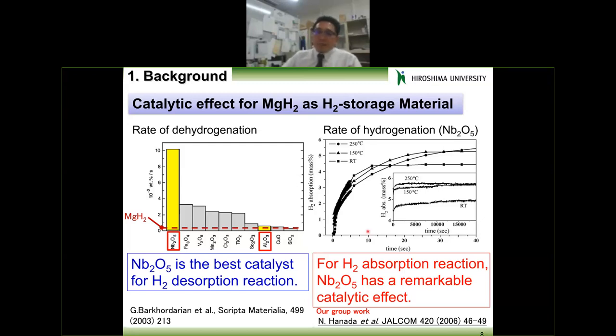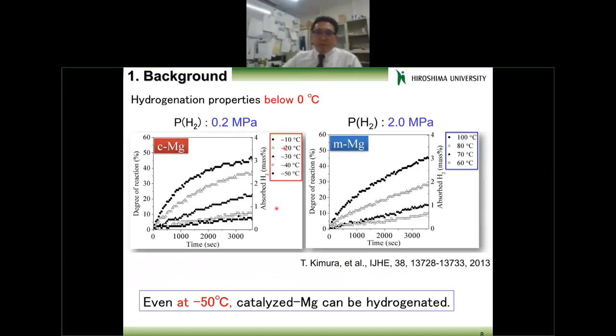And of course, this is just below room temperature, at -10 to -50 degrees C. Even at such quite low temperature, that magnesium can absorb hydrogen. We compared non-catalyzed magnesium and catalyzed magnesium, and there is quite a big difference. But anyway, we performed this hydrogen absorption below 0 degrees C. That is also the first time to report.